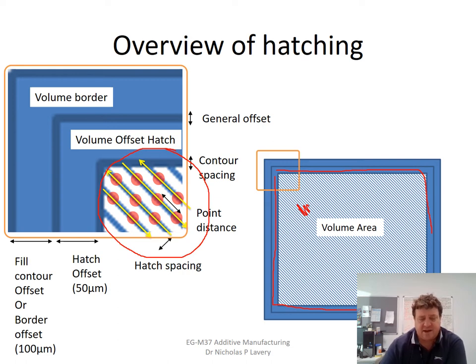With the Renishaw systems, the laser is fired as a series of almost single weld points. This is what we would call a modulated laser. It's not continuous. Each point is separated by a distance called the point distance, from there to there. The laser moves down, then comes back in the opposite direction, and goes back and forward and so on. The distance between adjacent lines is the hatch spacing. There are various other distances here, such as the hatch offset, typically around 50 micron, and the fill contour offset or border offset, which creates this volume border, typically about 100 micron.